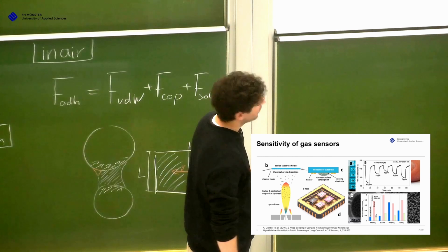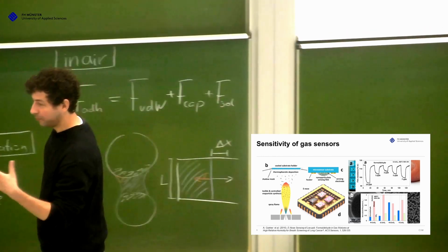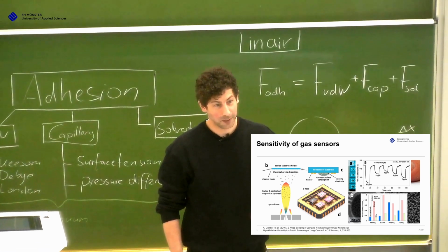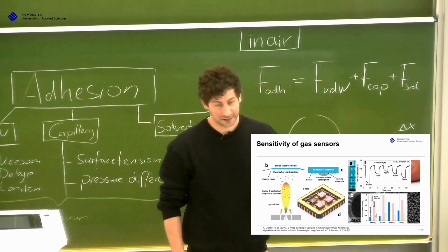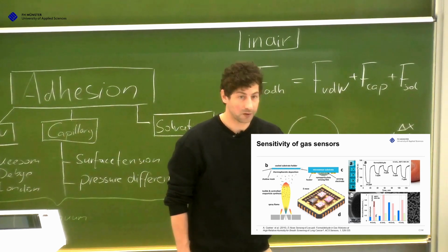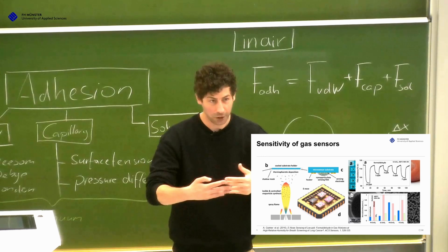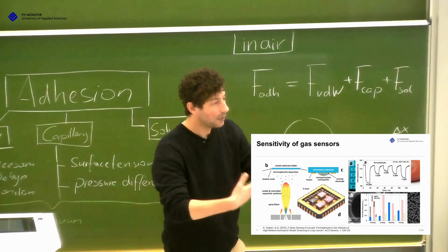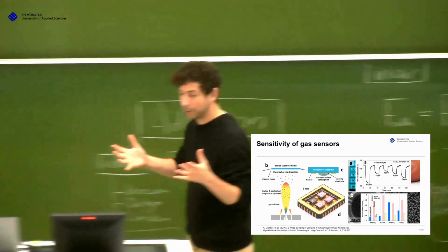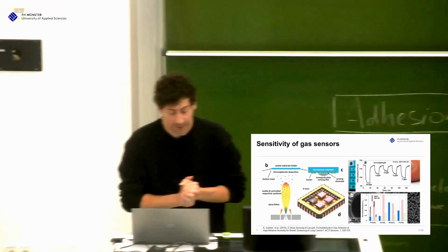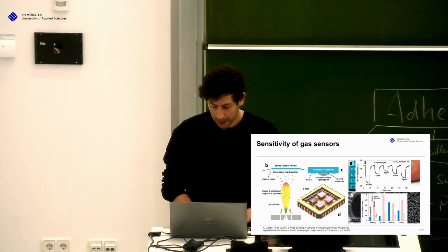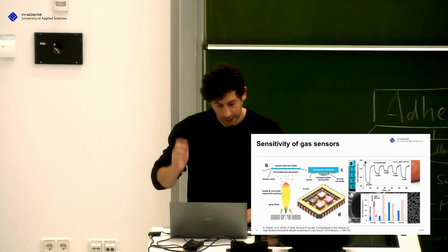Ti. And what you can do is, if you know all 4 materials, you can put all 4 into your sensor, you make a little bit of statistics, and then the sensor for sure tells you, okay, the amount of formaldehyde is too high. So one material is not selective enough, but the combination of different materials gives the selectivity to the sensor. And in this case, you can make really nice gas sensors by these flame processes, extremely cheap, extremely sensitive, extremely selective, and that's quite nice.